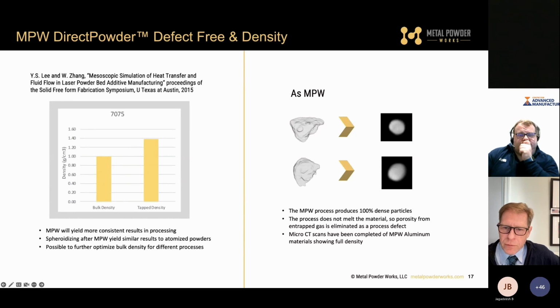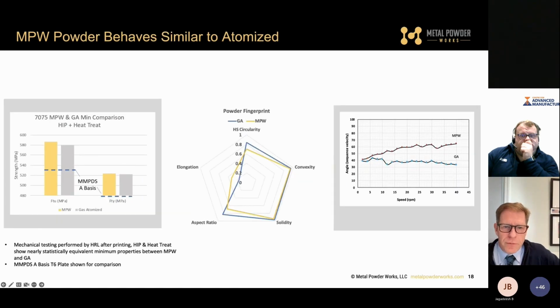So, what you don't see here, because you can see straight through it, is that we don't have any defects. We convert effectively whatever the bar stock material is. We'll retain the microstructure. We can retain the heat treat or temper of the bar stock into the powder, because we don't really introduce any heat into the product. There's no melting. We don't change the state of matter. So it's a very interesting process from that.